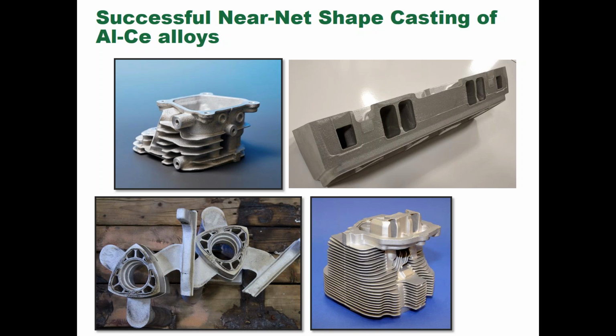In the bottom left we're looking at very lightweight rotary engines using this alloy, and these are rotors that would potentially go into a rotary engine from this material. And on the lower right, Eck Industries cast a lot of cylinder heads, and they're very difficult to pour and require special handling. And what we did is we poured using the same gating system that we do in 242 alloy, where the heads are normally produced. And we got very, very good results out of that.